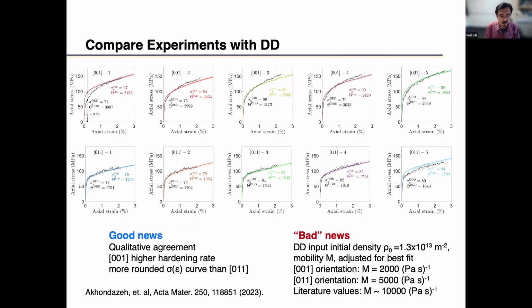Okay. For copper, there is a literature value. That literature value comes from both experiments and simulations. That's on the order of 10 to the fourth. In fact, it's even bigger than that. It could be 5 times 10 to the fourth, okay? But we found that if we use that mobility law, it won't agree with the experiment. The stress strain curve we predicted will be much lower. So you have to use a smaller mobility law parameter to agree with experiments.